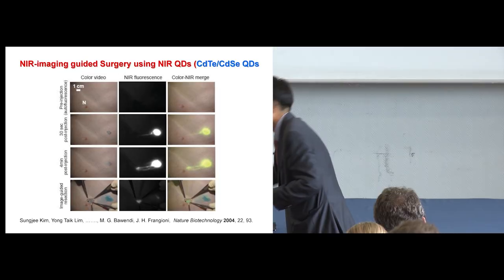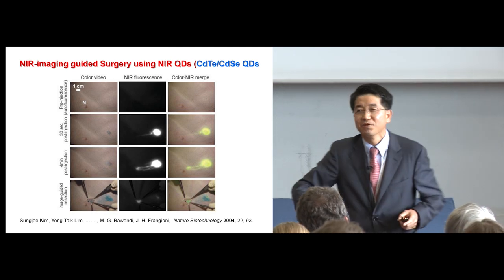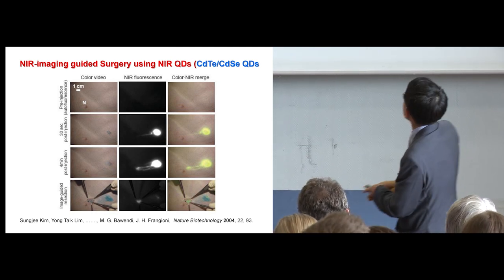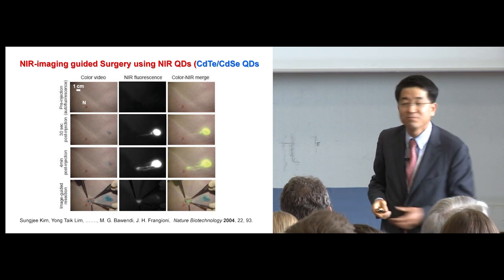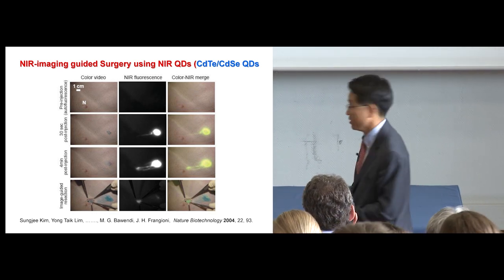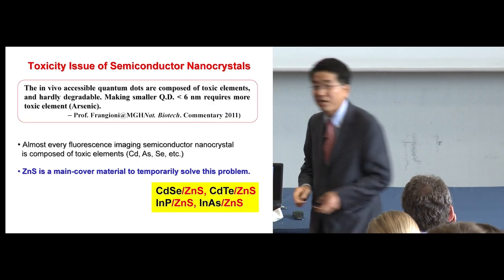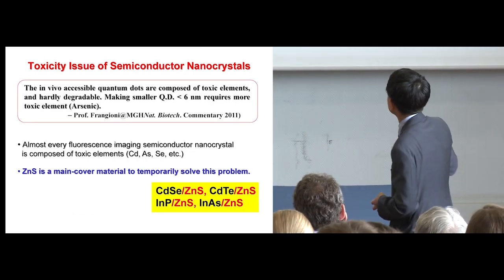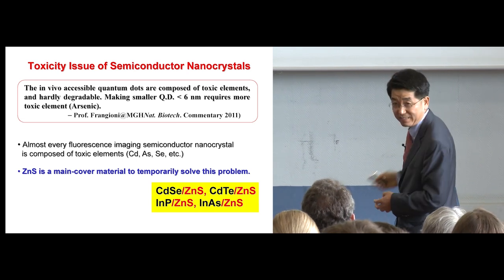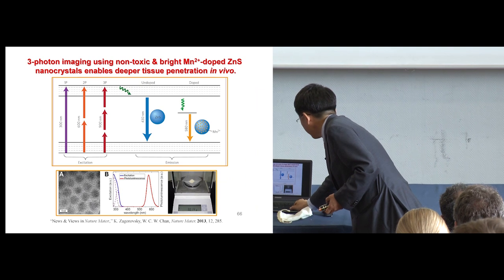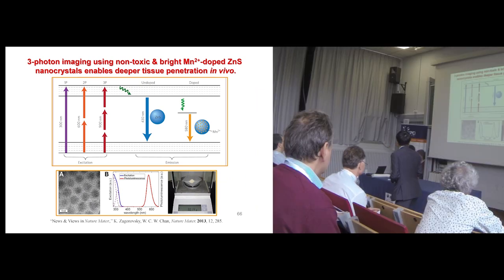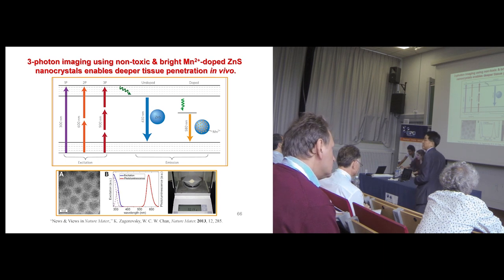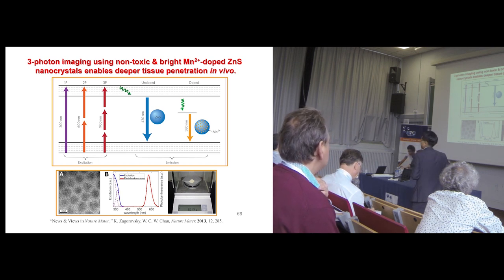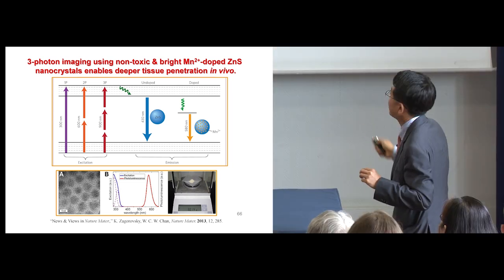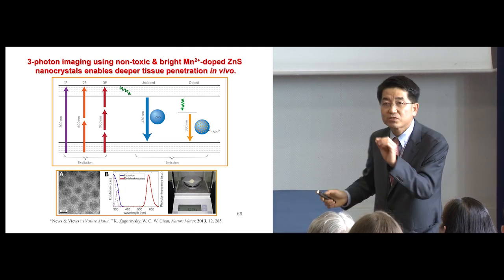Basically, Sungjee did a wonderful job using type 2, NIR absorbing quantum dots, CdTe/CdSe core-shell structures, to do this kind of swine model sentinel lymph node imaging. This is wonderful work. But his collaborator, John Frangioni at MGH, stopped working on this obviously because of the toxicity issue. That's why we take a look here at three-photon imaging using manganese-doped zinc sulfide nanocrystals. And it took about 5 years to make bright enough manganese-doped zinc sulfide nanocrystals.